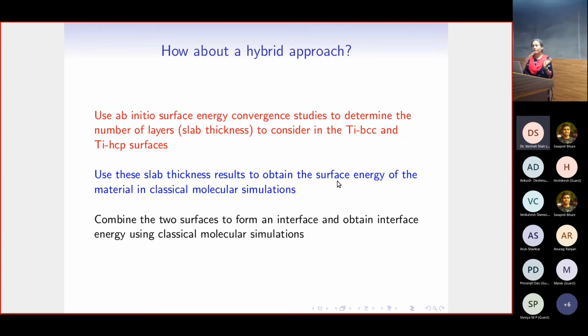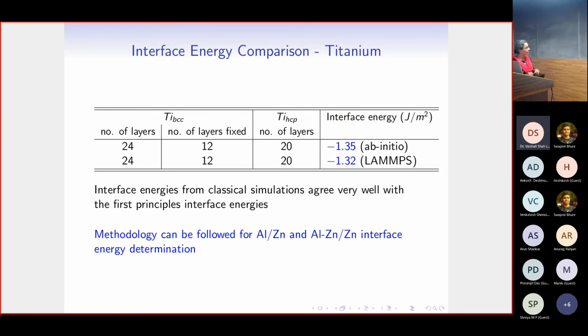Now we know how to calculate the surface energies and what slab thicknesses we need to work with. We just need to make sure whether our ab initio results now agree with our classical simulation results. And this is what we see. We have a success story here, because we took the information for the convergence of surface energies from ab initio, put it in the classical simulation, and simply repeated the same calculation, looking at the interface energy. Interface energy is just the difference between the total energy and the individual surface energies. Even if those individual surface energies do not agree with the ab initio surface energies, the differences do agree. This is a very nice agreement between the ab initio and the classical simulation results.